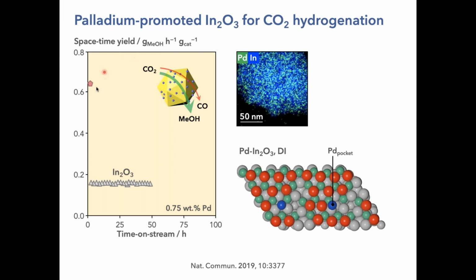Well, luckily, this is the case in the beginning. So if this is the base activity of indium oxide, and you put palladium on indium oxide by dry impregnation, DI, still trying to form very dispersed species, because we know that if we form palladium nanoparticles, we are going to alter the selectivity patterns towards CO, because palladium nanoparticles are extremely good in catalyzing the reverse water gas shift. So we will violate our intention of keeping the selectivity pattern to methanol of indium oxide. Indeed, by doing that, very dispersed palladium species, atomically dispersed on the indium oxide particles, we get a significant promotion of space-time yield, say a factor of 3 in this example.